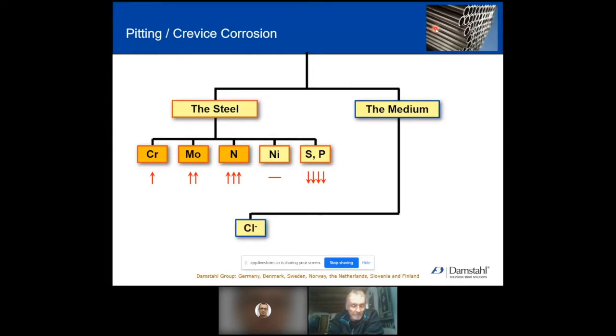The medium: chloride, salt, it's uniformly bad. The more chloride, the worse. The higher the temperature, it's exactly the same, worse. Corrosion potential, that's actually the cathode reaction. The anode reaction and the corrosion, that's the steel dissolving, the metal ions being oxidized. But the cathode, that's the one eating the electrons. Normally, in most cases, it would be oxygen. The higher the oxygen level, the worse.